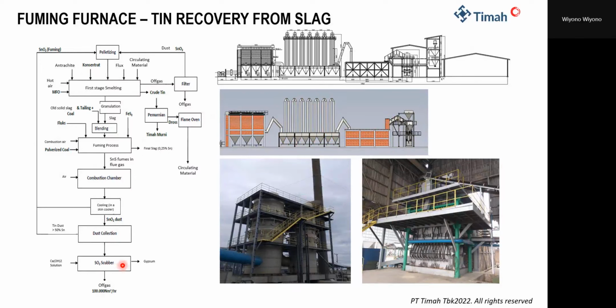So the results from the fuming furnace: the first is tin dust, and then the final slag. Our target is below 0.3%. Because of environmental regulation, especially for sulfur oxide gas, in the fuming furnace we also install a scrubber. In the scrubber we react the sulfur gas with Ca hydroxide to make gypsum, and the other byproduct in the fuming furnace is gypsum.